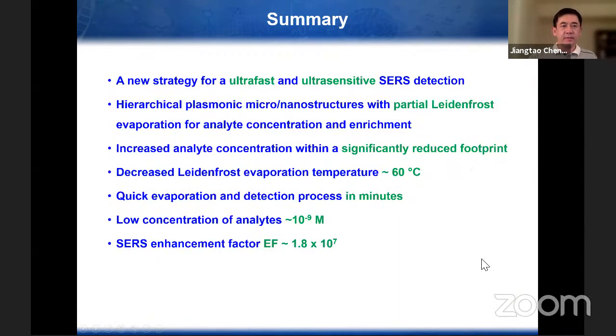And as a summary, we're using the wetting properties of the SERS platform as well as the plasmonic nano antenna structures, and we reached very fast analyte SERS detection in minutes instead of hours. And also we can detect nanomolar analytes, and the SERS enhancement factor can reach above 10 to the power 7.